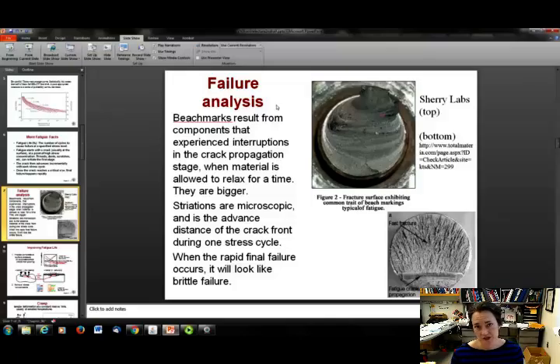They're bigger, they're visible to the naked eye or with just a simple little handheld lens. Now there's also, if you look at the part under an electron microscope or a high power microscope, you can see what are known as striations inside these beach marks, and the striations are microscopic, and it shows you the advance of the crack front during just one stress cycle and looks like little ripples.